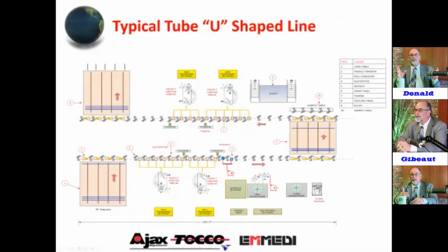But you can see here, the point I want to make is you've got a 500 hertz here on that first power supply and a 1 kilohertz. So the 500 hertz helps you with that depth of penetration. Even though it's shallower below the magnetic Curie, we can go with a lower frequency to help us get as much depth as we can on this front end. And then we come into the quench components.